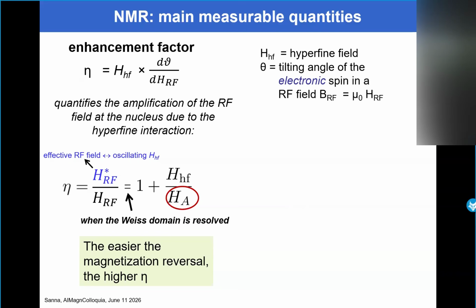When you apply a radio frequency field, if the material is soft, so the anisotropy field is very low, it means that the magnetization can follow the radio frequency field. If the material is very hard, so with a very large hysteresis loop, then, of course, the stiffness, if you like, is much bigger, and so the electronic magnetization cannot follow the radio frequency field. And so this amplification effect in the latter case is much lower. So it means that the radio frequency field is only the one produced by the coil, not amplified by the presence of the ferromagnet.